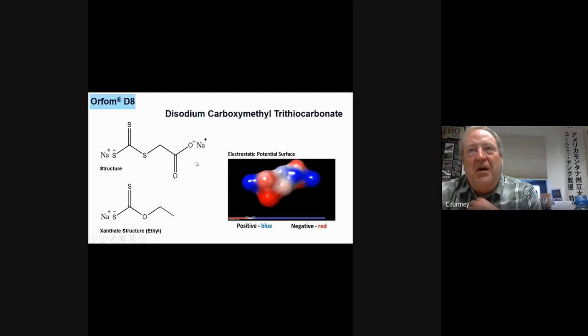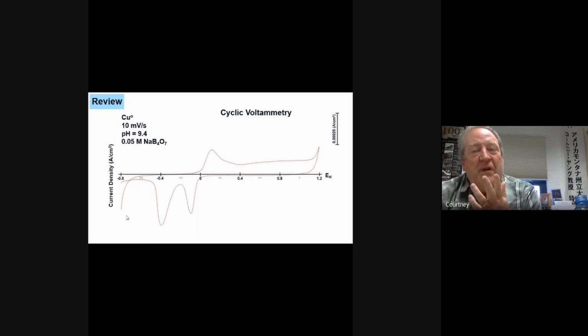So this molecule might respond very similar to xanthate on this side, but of course this molecule is charged on both ends, and this molecule is hydrophobic on this end and hydrophilic on this end. So we're not going to do anything fancy. We're going to take a look at some cyclic voltammetry, and we're just going to look at copper metal at pH 9.4, and that pH comes from 0.05 molar sodium borate. Our scan rate here is 10 millivolts per second.